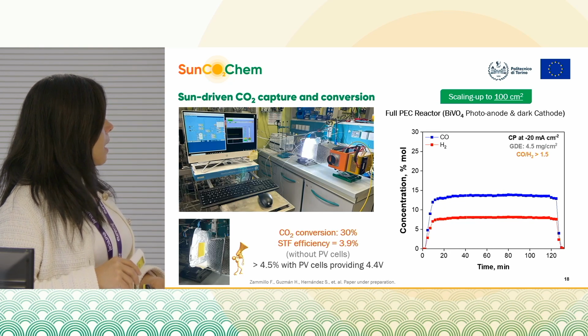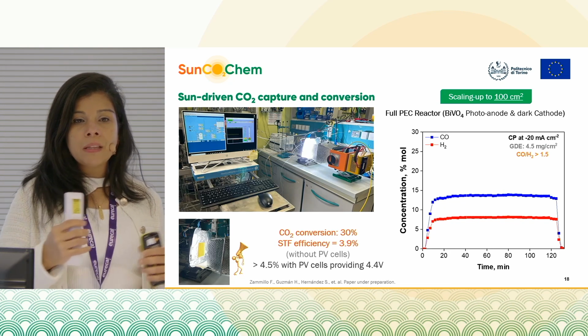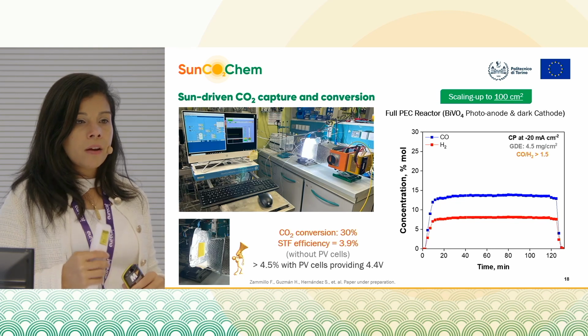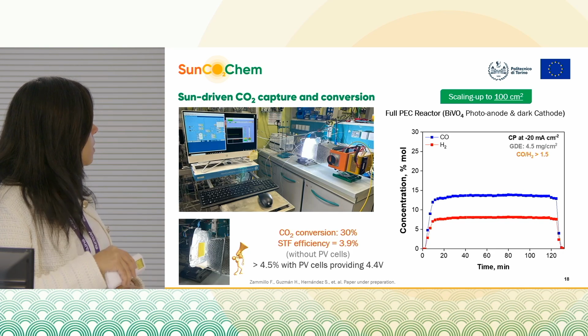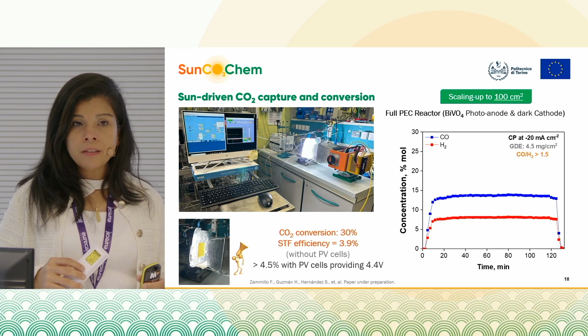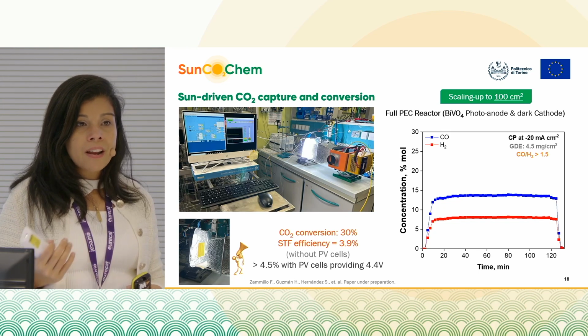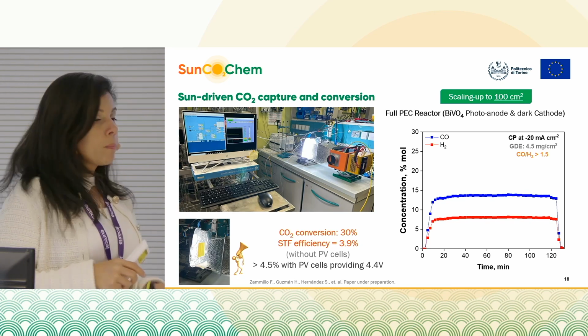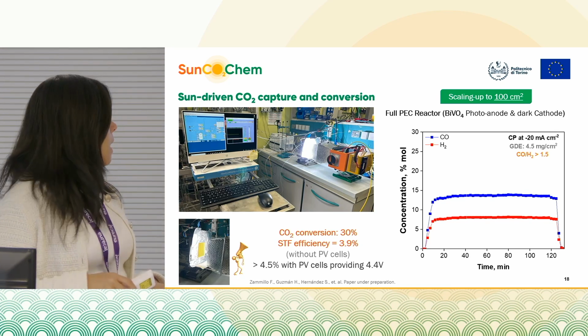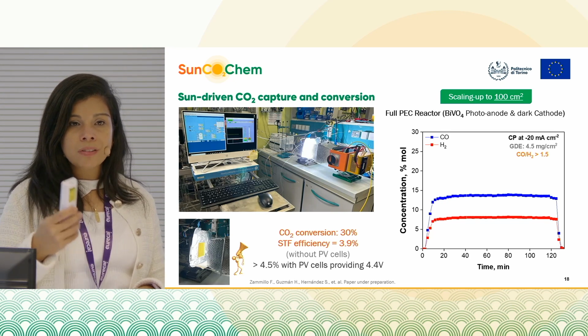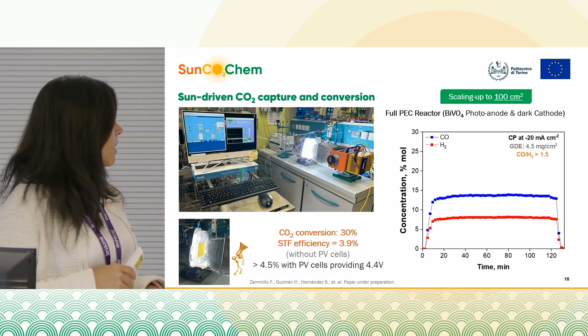With those tests and after several optimizations of process parameters, catalyst loading, and ink preparation, components in the ink, etc., we were able to achieve a CO2 conversion efficiency of 30%. That is actually one of the targets for achieving industrially relevant application of this technology. And we were able to demonstrate up to 4% of solar to fuel conversion efficiency that could become 4.5% if we use photovoltaic panels, the ones that are being used in the final demonstrator for providing the voltage to the process.